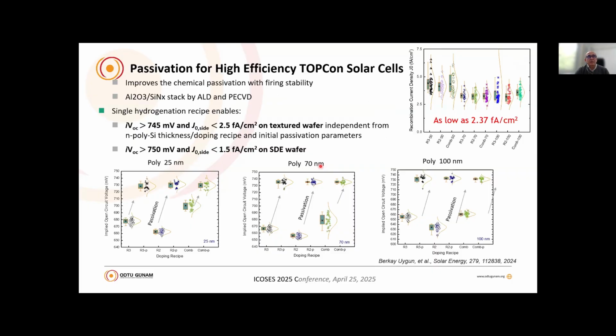So, these are just some experiments showing the passivation quality we have reached so far. We have looked at different polysilicon layers on the backside, and we have reached extremely good passivation values. As you can see here, the implied VOC values have been close to 750 millivolt, which is maybe one of the highest in the existing literature.